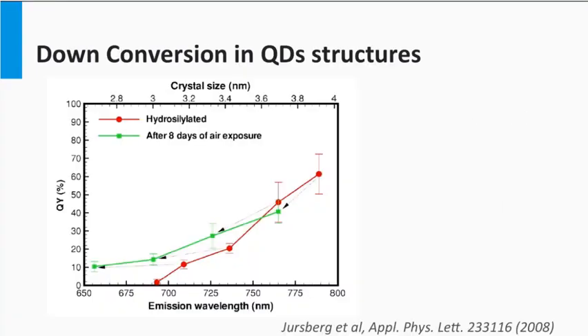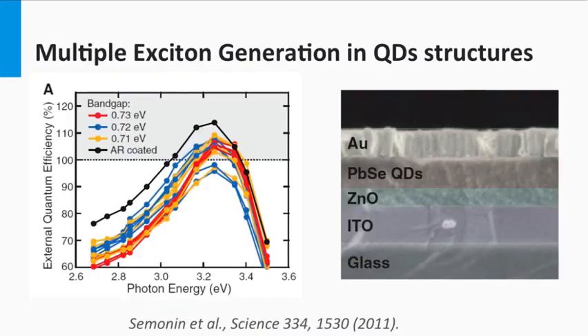Here you see some experimental results on down conversion based on silicon quantum dots in a narrow spectral range from a paper of Jursberg et al. The horizontal axis represents the photon emission wavelength. At around 799 nanometers, a down conversion efficiency of 60% is achieved.